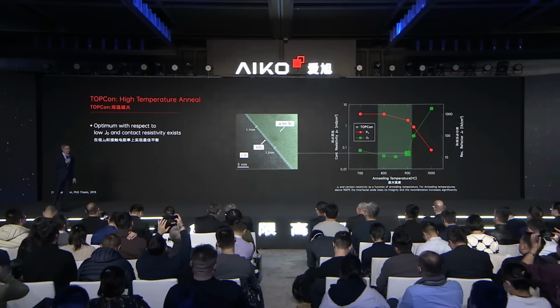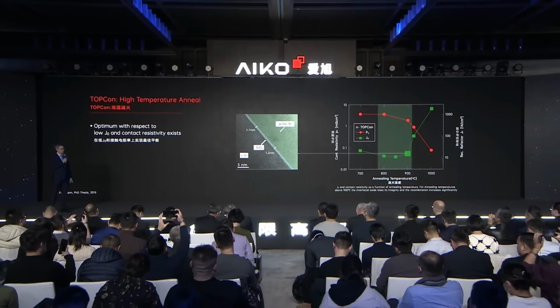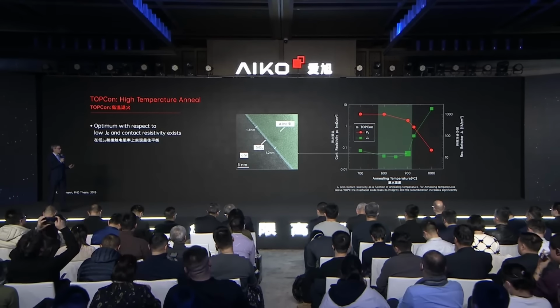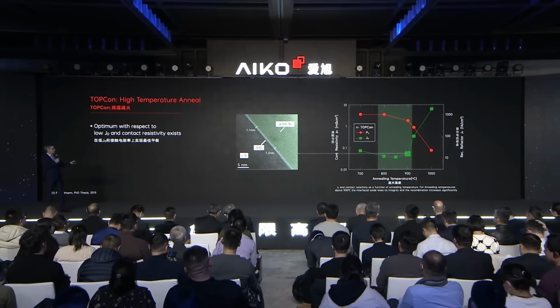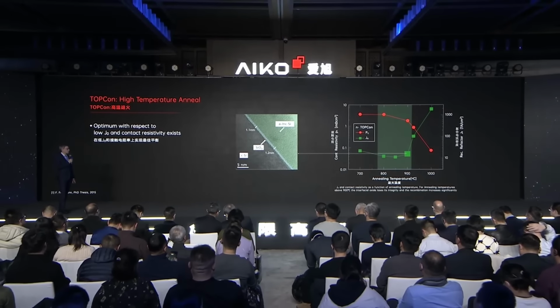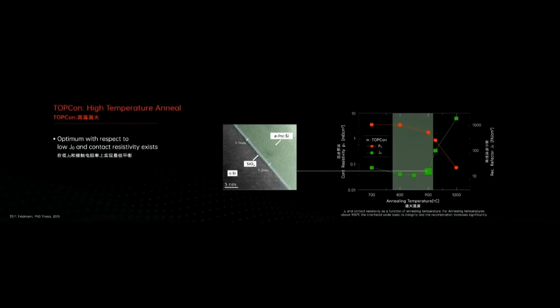So the high temperature anneal is important for the TOPCon structure because it forms the contact, and if we are in the optimum annealing range, then you can see that we get low recombination values shown in green, and also reasonably low contact resistivity values. And here, at my time at Fraunhofer, we took a TEM image of such a contact, and you can see that the tunnel oxide is nicely intact. It's very thin, just 1.1, 1.2 nanometers, and continuous across the surface. And on top, in green, you see the polysilicon layer with the different crystal orientations.